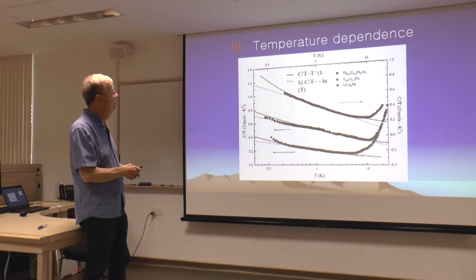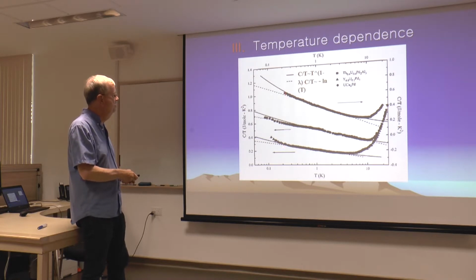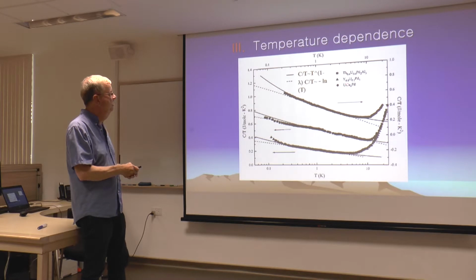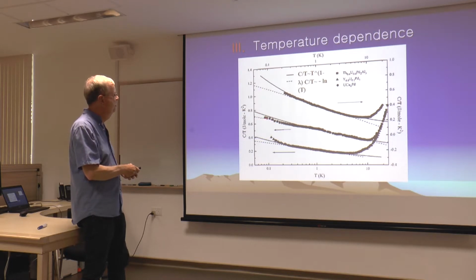again, this has been messed up by our fiddling with the dimensions. The temperature dependence makes a difference, and sometimes you have to go to low temperature, 100 millikelvin, to find out what temperature dependence it is you've got. And so here's an example with one of these heavy fermion systems that down here at low temperatures you can tell that it's more of a log temperature dependence than it is a power law temperature dependence, T to the exponent 1 minus lambda. This lambda should be up here, sorry about that.